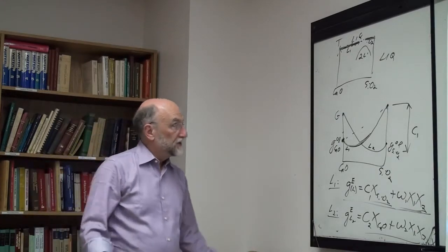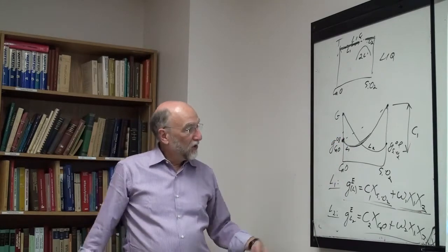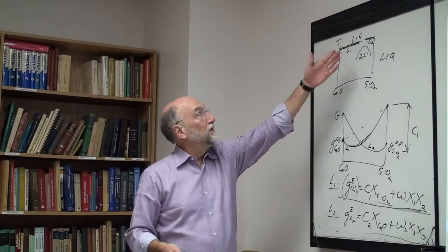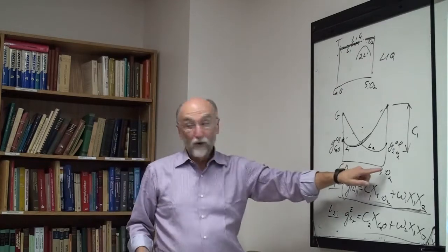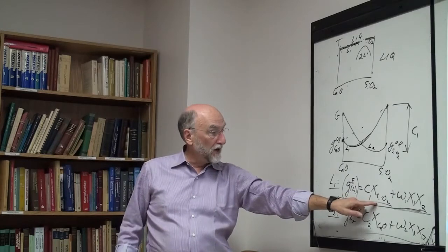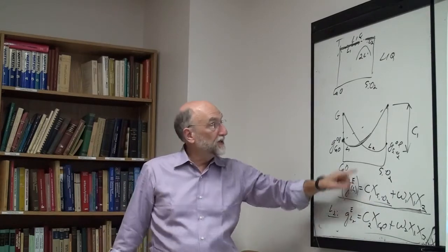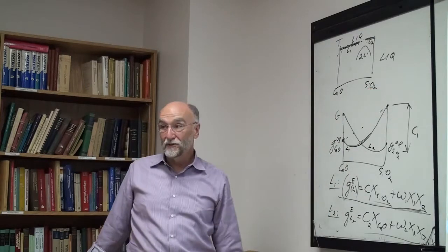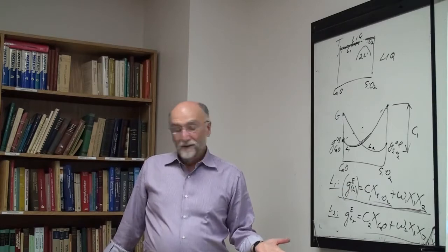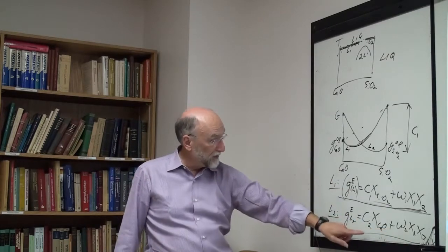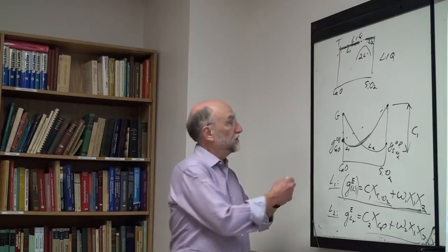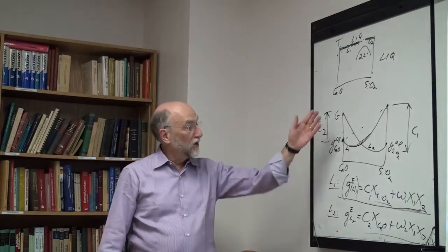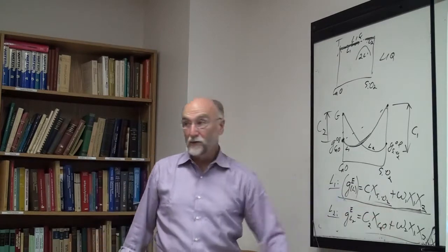Okay, but the trouble with this, of course, is that these don't meet in the middle. Or another way of looking at it, what if we use this equation here? The liquid is one phase, so Gxs of course has to be 0 at both ends. But obviously this equation, when x silica equals 1, is not 0, it's equal to C1. So the Gxs of this phase is not 0 at this end, it's up here. So this equation clearly cannot apply over the entire composition region unless C1 equals 0. Similarly, this equation has to go to 0 over here, but it doesn't, because when X calcium oxide is 1, it's equal to C2. This distance here is C2. So you can't do it. If you want these equations to apply over the whole range, C1 has to equal C2 equal to 0, and omega 1 equal to omega 2, and you get a regular solution.